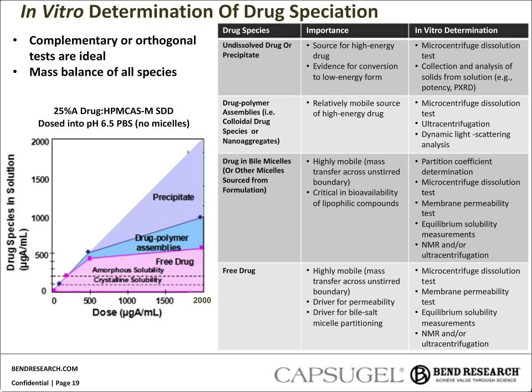Finally, back to the theme that SDD performance can be measured and modeled, we like to use orthogonal or complementary tests to completely understand and validate our mechanistic beliefs. We called out drug and micelle-based concentrations as key, and I'll just summarize in the far right column that we can use a stronger centrifugation step to isolate the nanoparticles from the free and micelle drug. We can use NMR because nanoparticles are invisible to NMR detection, or we can use tests with permeability built in that only rely on the free drug concentrations. We can also use a function of dose or micelle concentration to build a holistic picture of the performance dependence and help predict in an in silico environment how these things will perform.